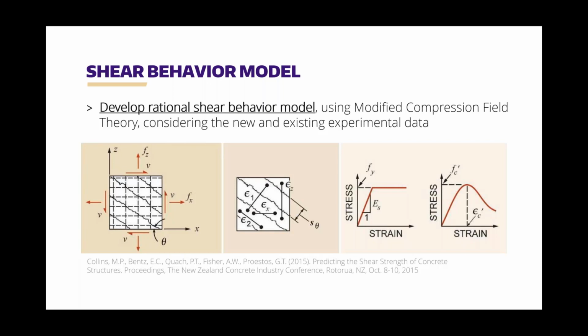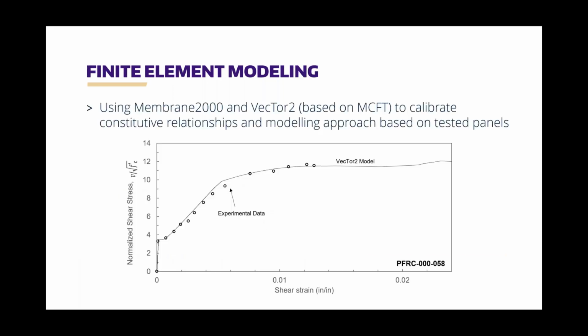So you can see kind of starting from the mechanics on the left, looking at principal strains in the panel in the middle, and then converting those strains to stresses using constitutive relationships, which we can then calibrate to what we've used, what we have in the test. So we have a student right now that's looking at this in both Membrane 2000 and Vector 2. They're finite element programs that are both based off of the modified compression field theory.